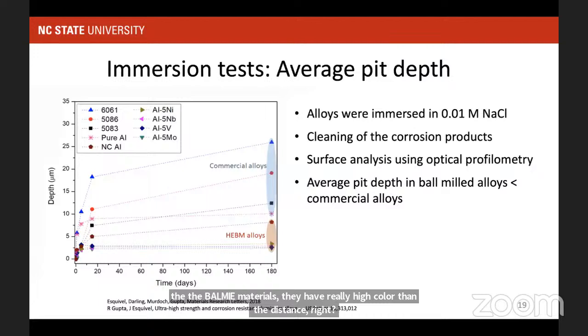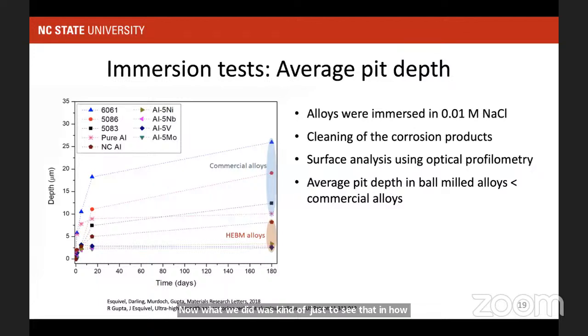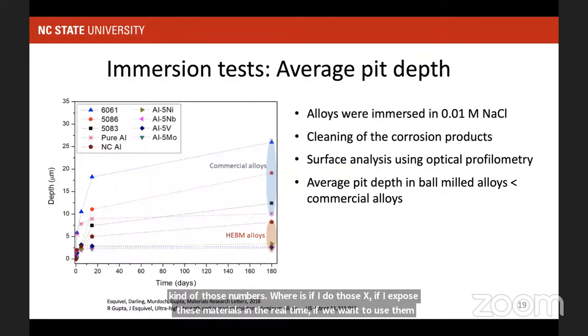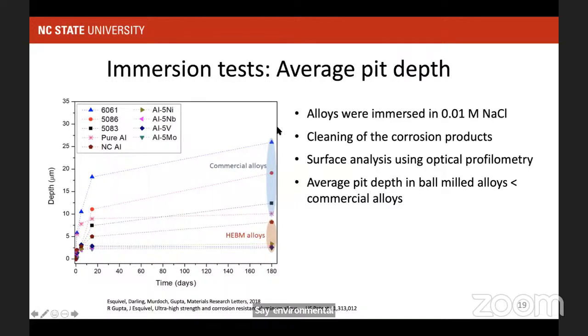Now, what we did was to see how those numbers vary if I expose these materials in real time, if we want to use them in, say, environmental exposure, in seawater and things like that. So we immersed these alloys in 0.01 molar sodium chloride for 6 months, and we were monitoring the growth of the localized corrosion, the growth of the pits, right? For comparison, we took the commercial alloys and pure aluminum, which are really corrosion resistant. If I take 7075, those high strength ones, the pit depth would be really, really huge. But even comparing those corrosion resistant alloys with the ball mill alloys, you see there is a huge difference.